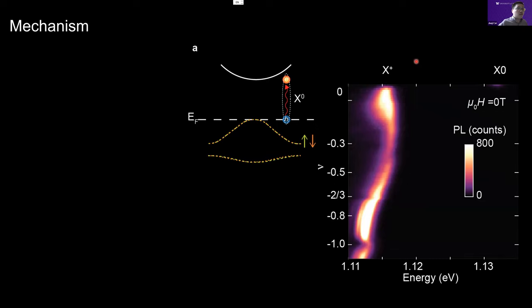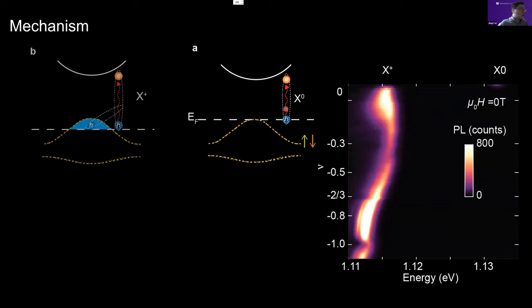Actually, if you take the full PL spectrum of the system, you can first see that in the undoped region, the forming of exciton dominates. As you start to dope the system, your Fermi surface will have holes on it, and then they will bond with the light-induced exciton to form trion. So this is the trion emission over here.